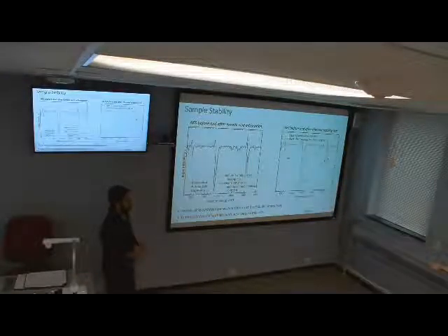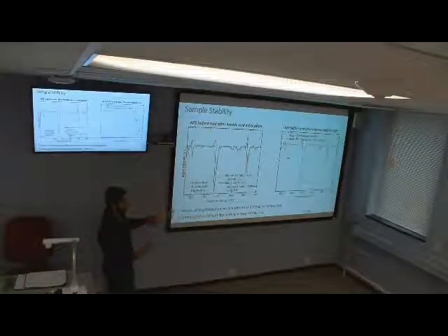You also compare spectra when carbon dioxide is filled into the chamber. Yeah, with the carbon dioxide too. With carbon dioxide we also have decomposition of the perovskite, but the temperature is somewhat lower than with formic acid. With carbon dioxide, it starts to decompose around 530 Kelvin, but with formic acid it starts to desorb around 600 Kelvin.